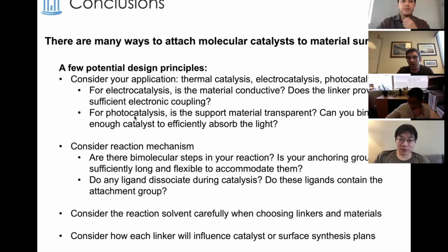If you're running a photocatalytic reaction, you should probably have a transparent support material so that the light isn't reflected away from the catalyst or the chromophore. And you're going to need to bind enough catalyst to absorb light. I alluded to that on the prior slide. And that may mean that you can't use a planar material, but you need a high surface area material to absorb enough catalyst to absorb the light.